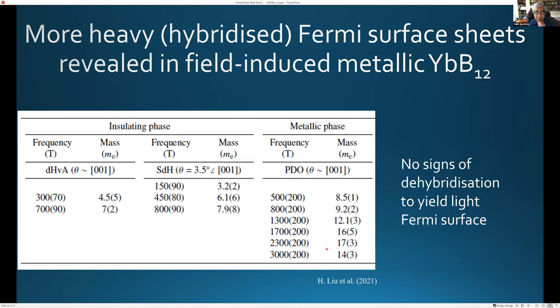Okay, so if I stick to the insulator, then yes, since you also made an analogy with ruthenium chloride, a possible theoretical model, and of course we don't know yet, could be that these are spinon Fermi surfaces in the insulator of ytterbium boron 12, at least. These are the F electrons that are somehow mixing with the conduction electrons once you go into the metallic phase. That's sort of what you're implying.